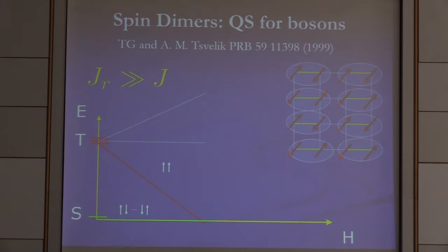So you immediately see that you will get a quantum phase transition here, something which can happen at t equals 0, when the triplet energy will go below the singlet energy. So you will go from a situation which is totally non-magnetized to a situation which is magnetized if you have put triplets inside the system.